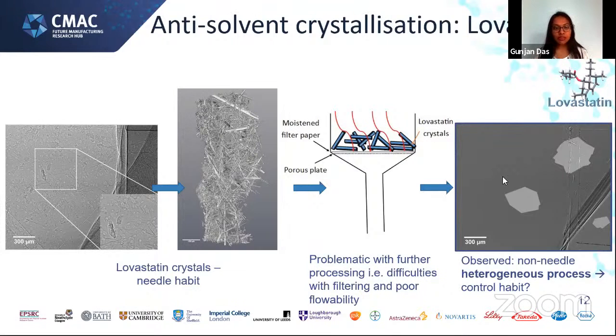When we were watching crystallization real time in situ, we have seen the needles here where I'm pointing out growing. And we have also performed a tomography, where we have done a 3D image, and we have seen them as well. Now, needles in industry or even in any labs are a huge problem because they cause difficulties with filtering, poor flowability properties, and of course also with pressing them into tablets.